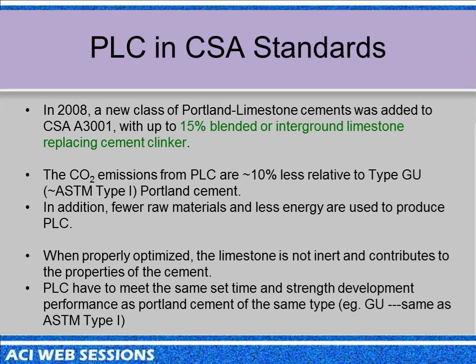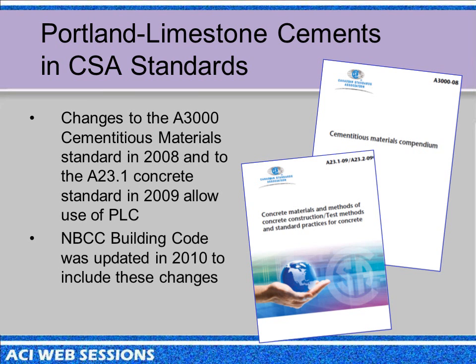It sets at the same time. It develops one-day strengths and early strengths and late strengths at the same time and the same rate as their straight Portland cement cousins. And our GU cement, the terminology used in A3001, is the same as ASTM Type 1, general use cement. So this went in the cement standard in 2008, then got incorporated into the concrete standard in 2009 to allow the use of Portland-limestone cement in concretes.